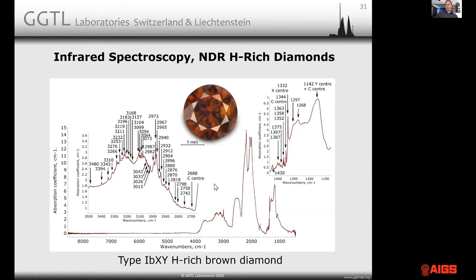If you calculate the nitrogen content, you will find out that the one phonon absorption is way too strong for a quantity of nitrogen. And you decompose it and you'll find this famous Y center. Now these stones are the ones that we still classify as brown, and the only ones that we would call H-rich type 1B diamonds.